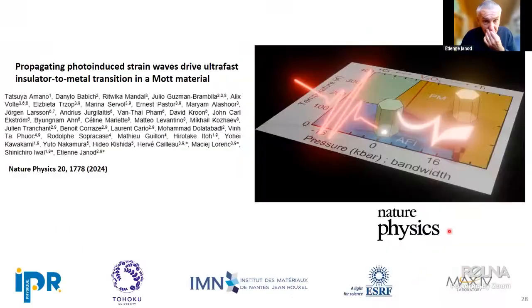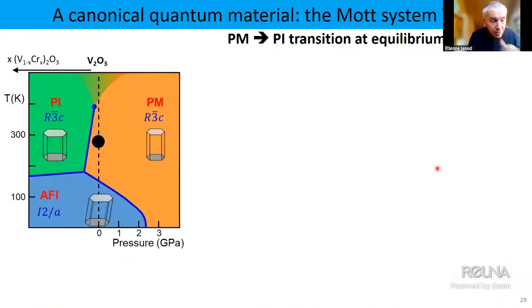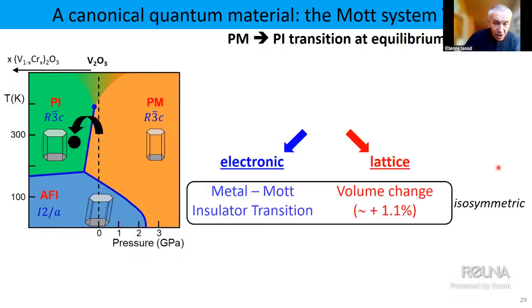All of what I'm going to talk about briefly now, we published last year in an article in Nature Physics. So let me be a bit more specific. We have used the V2O3 system, so you know this V2O3 system. And let me recall that in this system, the metal to Mott insulator transition, when we cross this transition, is completely isosymmetric, from the electronic point of view. We have a metal to insulator transition which does not break any symmetry. And we also have a change of lattice, but the change of lattice is only a volume change without any change of symmetry. So it's a purely isosymmetric transition.